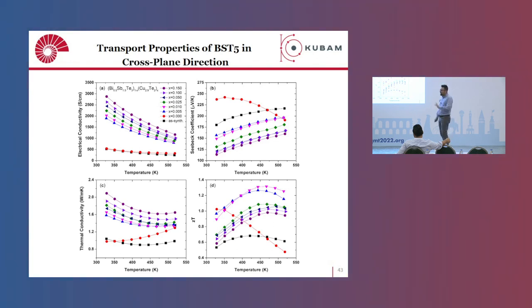Kind of, yeah. So that is the thing. Now, you can see that this is bismuth antimony telluride, again no copper telluride addition. This is called as-synthesized. The main difference between the black and the red is this. In the red, you may remember that the copper telluride is added by 10-minute ball milling after we synthesize this material. For the black, we synthesized this material and did 10-minute ball milling without any copper telluride addition. The other copper tellurides are also done in the same way, with 10-minute ball milling. So we wanted to show what is changing here.